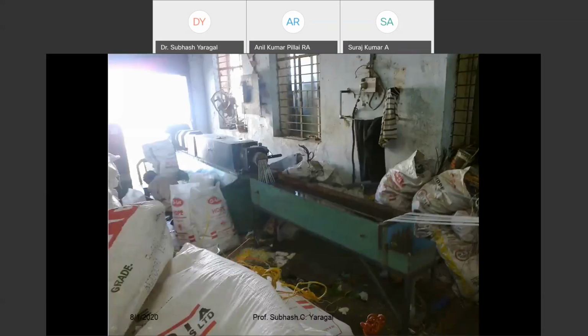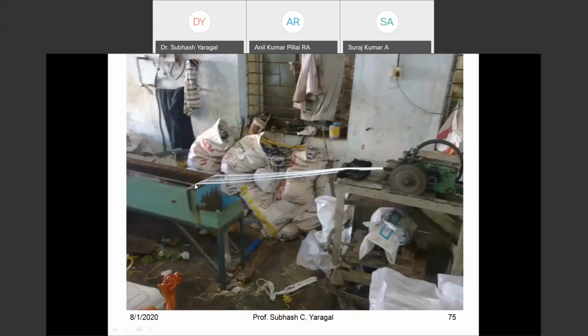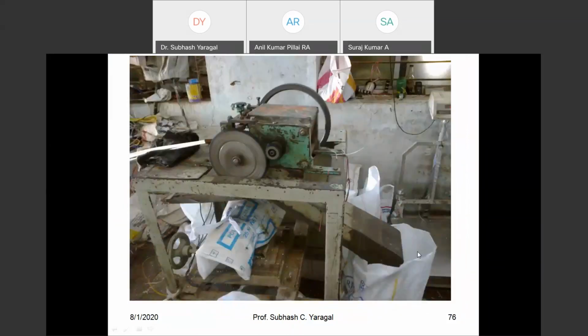Now this is a melt processing plant in Baikampady in Mangalore. This chamber is a heat chamber where all the domestic plastic bags have been put and melted. The melted plastic is extruded from this extruder and allowed to flow into the water bath, and you get cooled strands of melt processed plastic. From the water bath, we use a pelletizing or cutting machine, and these strands are cut into small pieces, which I'm calling pellets. These pellets are filled in bags, and it looks like this.